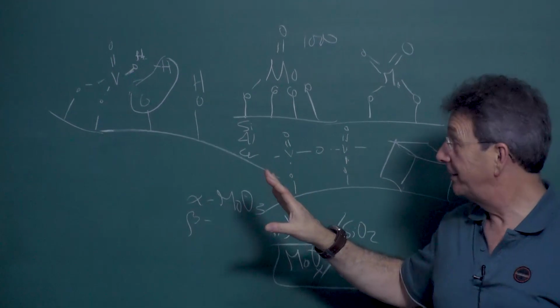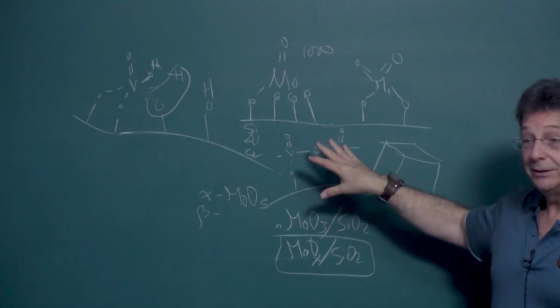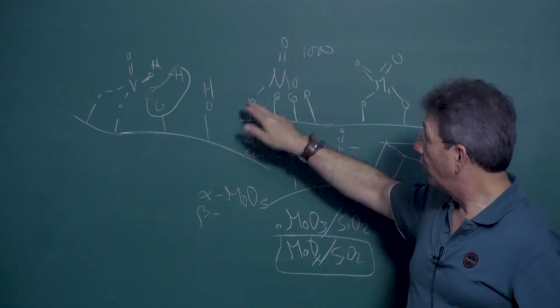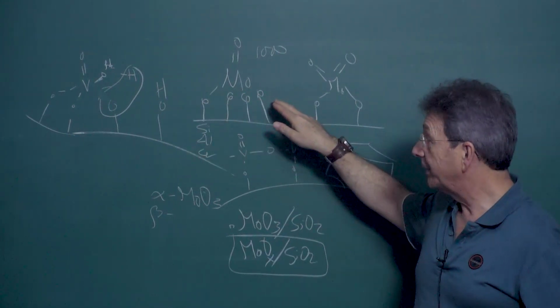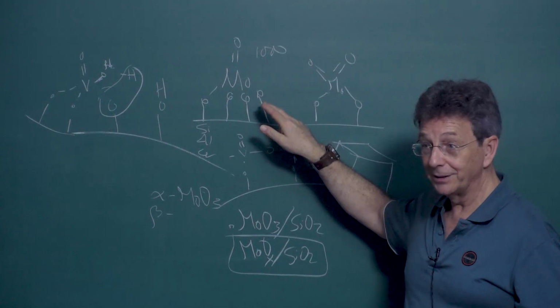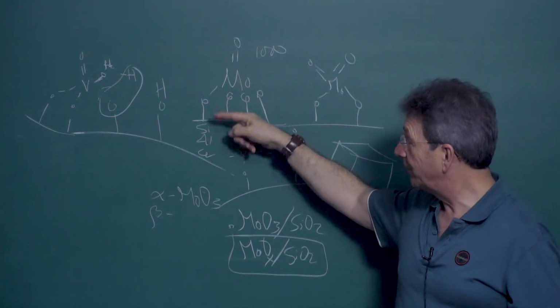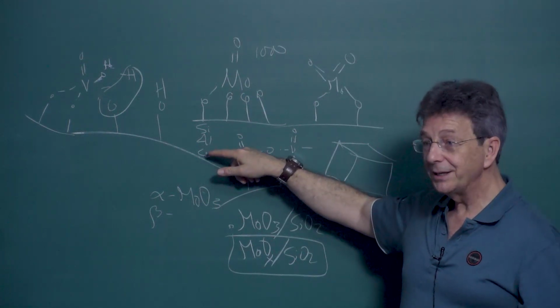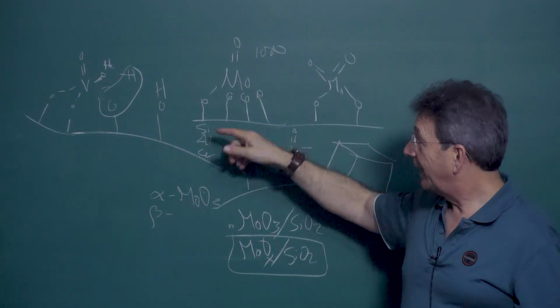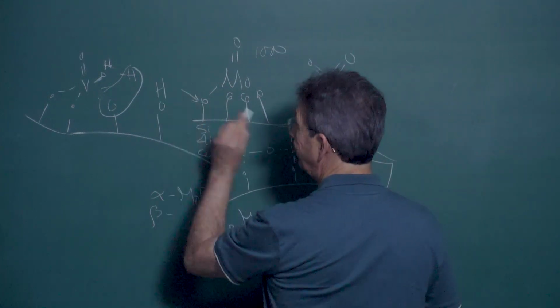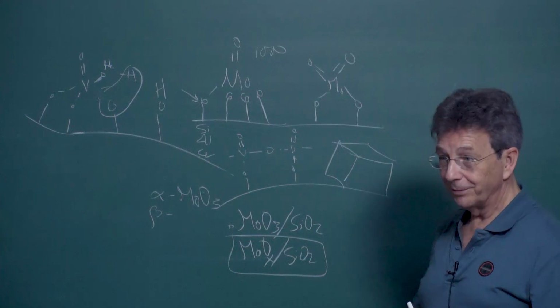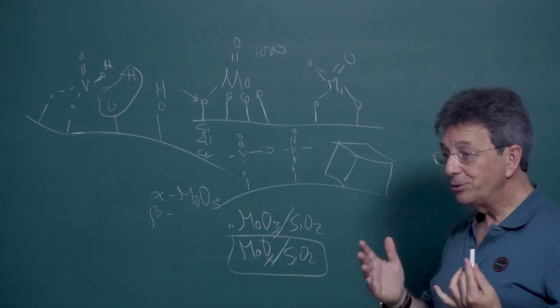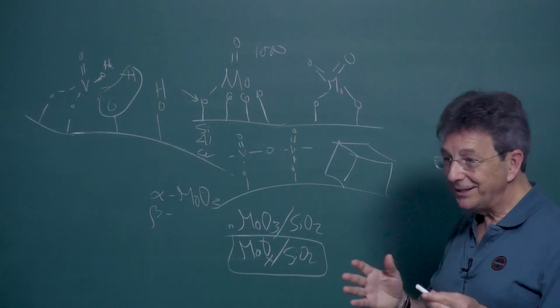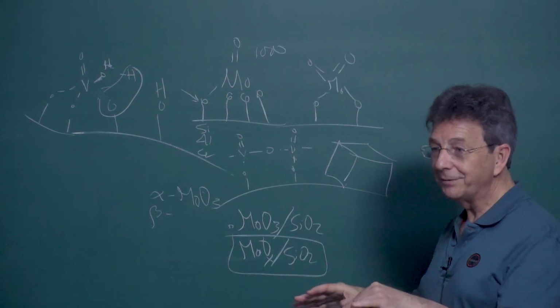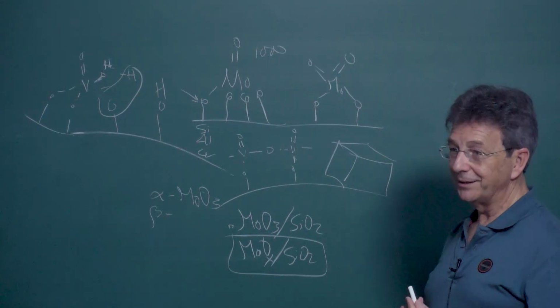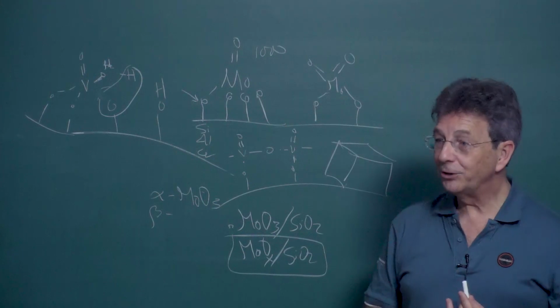And actually this is what makes it different, because typically catalysis is associated to the oxygen atoms. Which one? It could be the oxo, or could be the bridging one. And actually the bridging oxygen is much more accountable for much of the catalytic performance, because it's the one that is changing the most. If you have molybdenum on silica, on alumina, on ceria, the performance is very, very different. Typically this is the site where the reaction is occurring, and that is what makes it special. It's no longer molybdenum, or yes it is, but it is not as it used to be. It's molybdenum interfaced with something else, and that makes the catalyst special. Always the interface is making you different, is making you special.